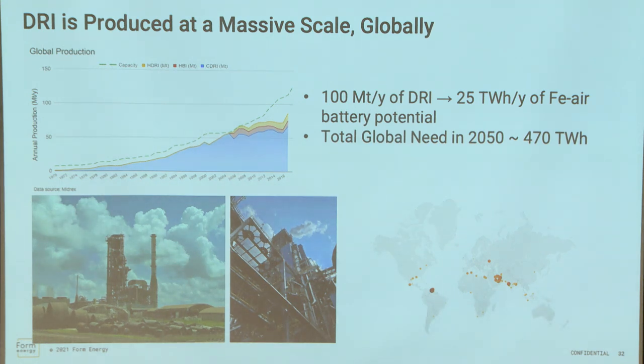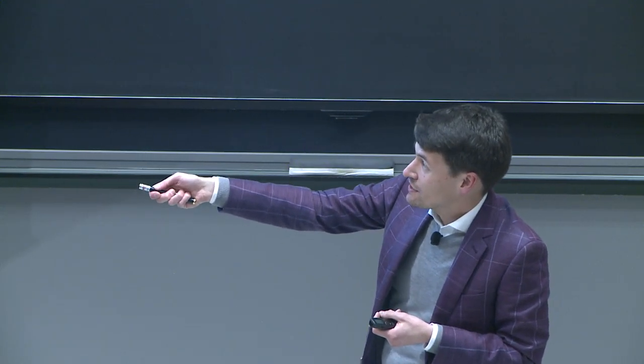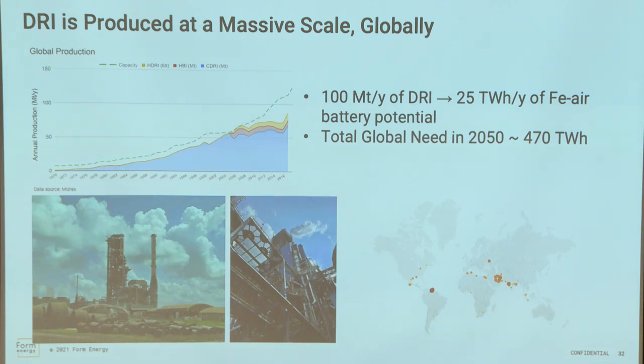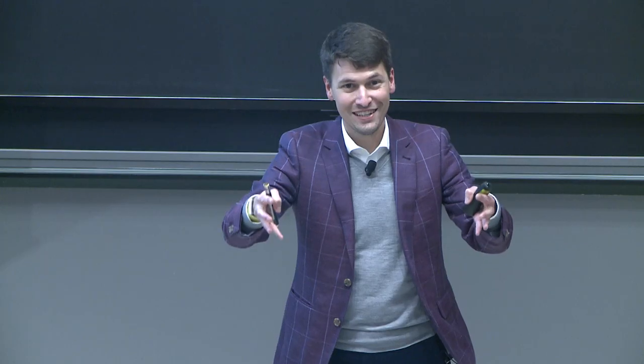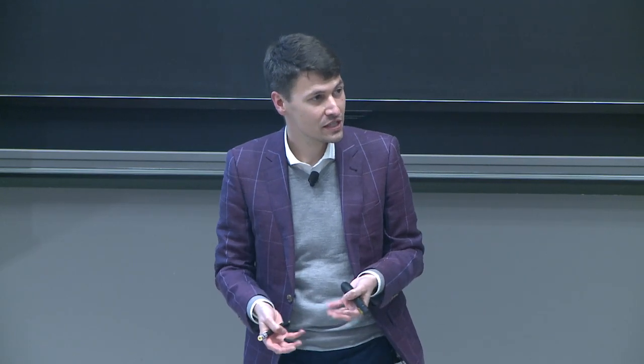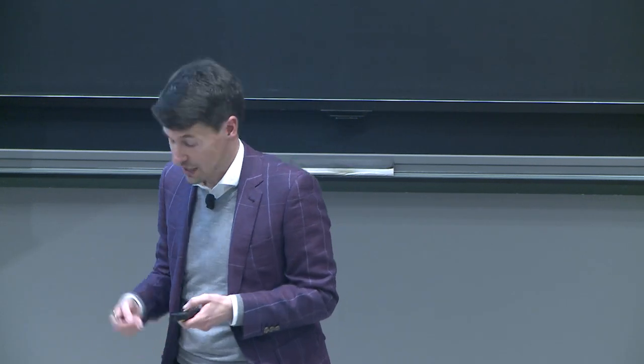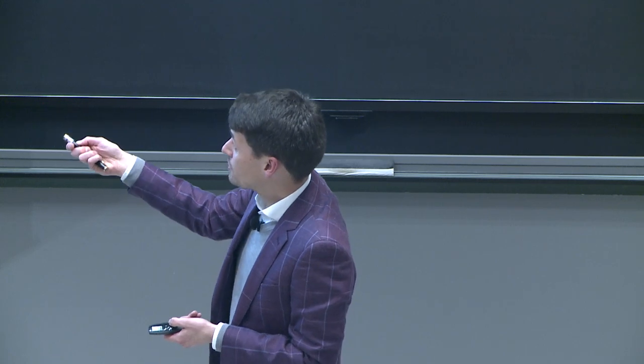And so these are really marvels of modern chemical engineering and material science, because what goes on inside of this is you put in pellets. I'll show you pictures of the pellets, or you saw the picture on the previous slide. They go in the top, hot gas goes up the center, they flow in opposite directions. The pellets work their way down and come out at the bottom as reduced iron metal pellets. And then those get shipped off to electric arc furnaces where they get melted down and turned into steel. So we make this all around the planet.